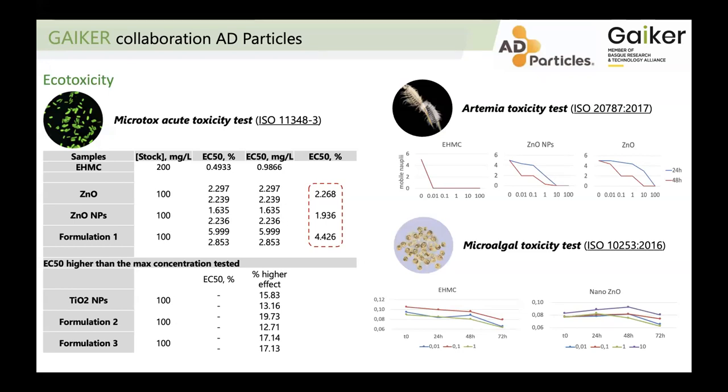The microalgae was less sensitive than the Artemia in these exposures. We can see an effect of the chemical filter, but it was not as evident as in the Artemia. But we can confirm that the chemical filter was more toxic to the organisms compared to the rest of the mineral filters. And concerning the mineral filters, the nano zinc oxide was the most toxic mineral filter.